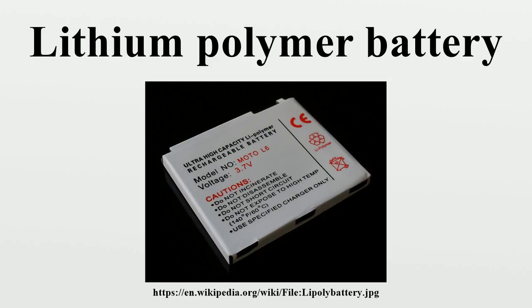Nishi mentions that Sony started research on lithium-ion cells with gelled polymer electrolytes in 1988, before the commercialization of the liquid electrolyte lithium-ion cell in 1991. At that time, polymer batteries were promising and it seemed polymer electrolytes would become indispensable. Eventually, this type of cell went into the market in 1998. However, Scrosati argues that, in the strictest sense, gelled membranes cannot be classified as true polymer electrolytes, but rather as hybrid systems where the liquid phases are contained within the polymer matrix. Although these polymer electrolytes may be dry to the touch, they can still contain 30% to 50% liquid solvent. In this regard, an open question remains on how to really define what a polymer battery is.